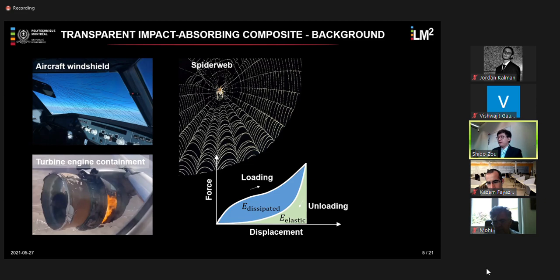of the system. It has been found that in spider silk, up to 70% of the total absorbed energy is actually this dissipated energy. And this high energy dissipation is especially beneficial for the spider web, because it can significantly reduce the oscillation of the spider web during prey capture. And of course, it can significantly increase the successful chance of prey capture.